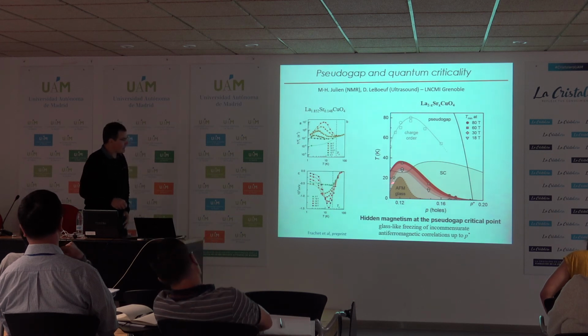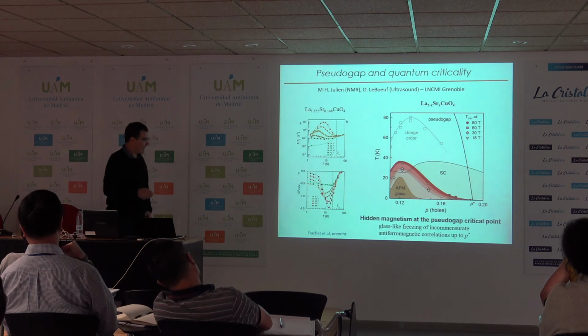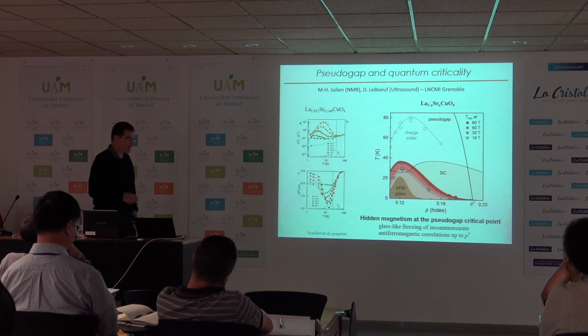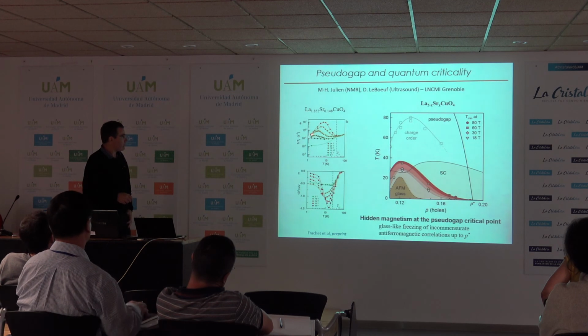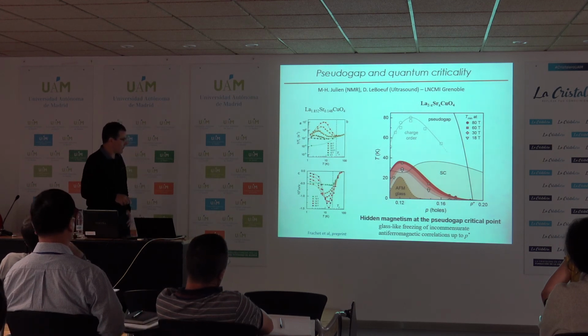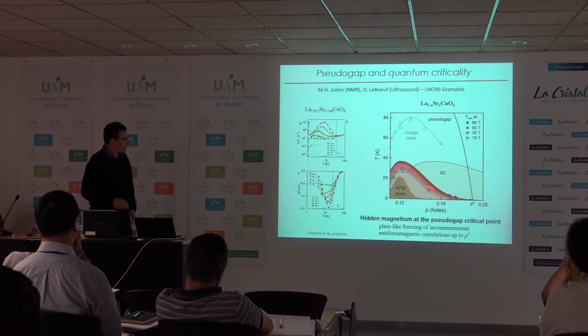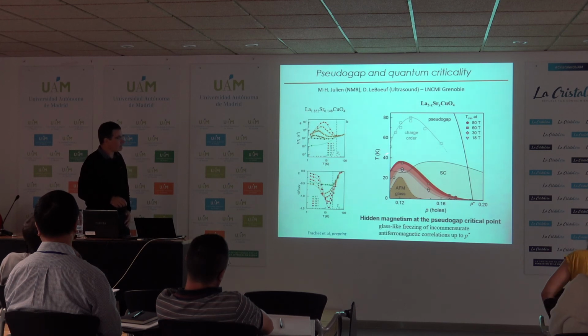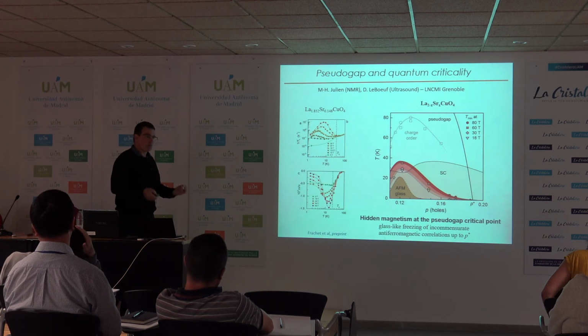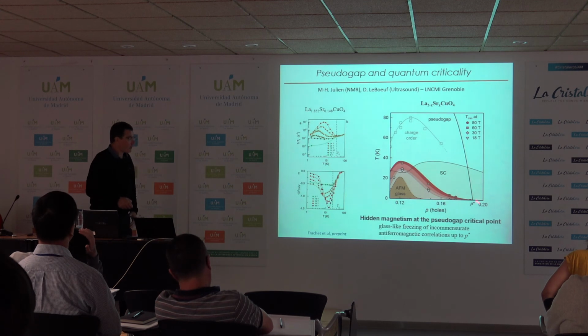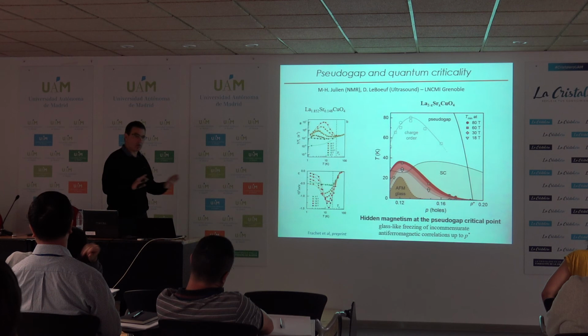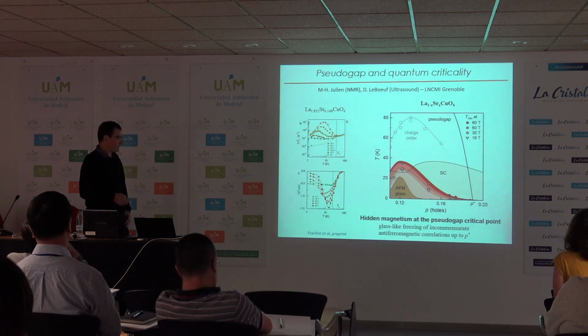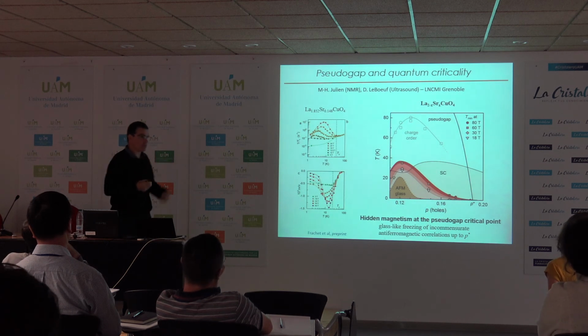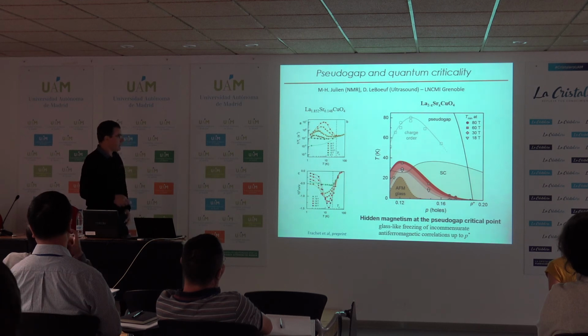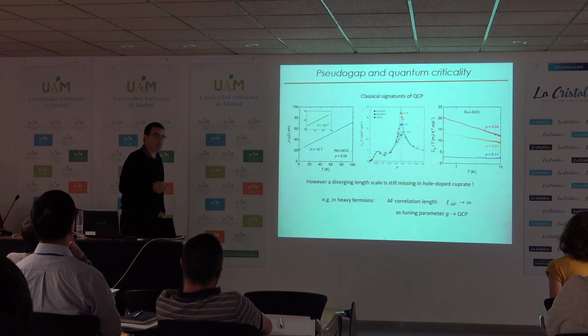It is well known in LSCO that around 12% there is a stripe-like phase with a glassy antiferromagnetic phase at zero magnetic field. What they discovered by performing NMR up to 45 Tesla, and David performed ultrasound up to 90 Tesla, is that this magnetism actually extends up to p star when you put a strong magnetic field to quench superconductivity. And of course they made measurements above p star where there is no more magnetism. This magnetism is really a glass-like freezing of incommensurate antiferromagnetic correlations. It's not purely an antiferromagnetic order, it's glassy. But this discovery may explain this kind of behavior.